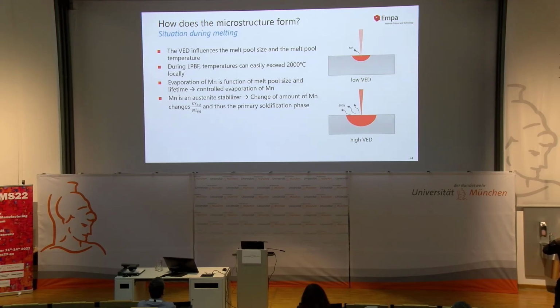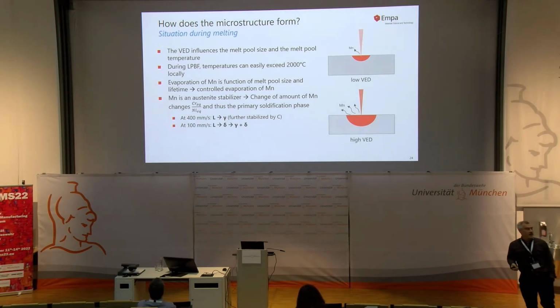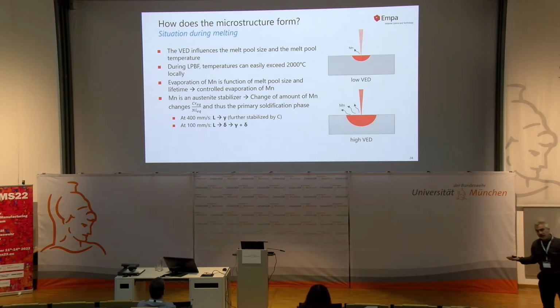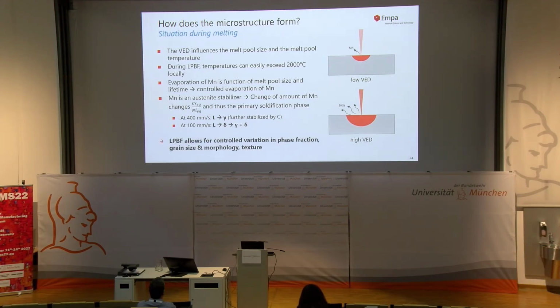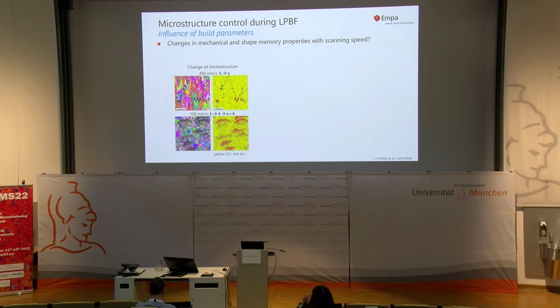So going back to what I explained before, we are somewhere on the brink between BCC and FCC solidifying material, and apparently we can switch between the two fields, depending on how much manganese we evaporate and depending on the cooling and solidification conditions. At 400 millimeters per second, at high scan velocities, we have a transformation directly into gamma, and that explains these large elongated grains. At the lower scan velocities, we have delta forming first, and then this solid state transformation into gamma and delta. And so it seems that laser powder bed fusion allows for controlled variation in phase fraction, grain size, morphology, and also texture.